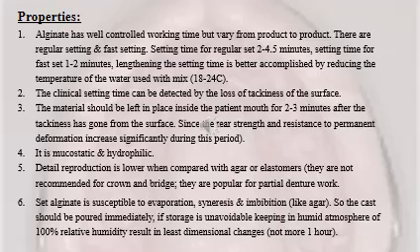2. Lengthening the setting time is better accomplished by reducing the temperature of the water used with the mix, from 18 to 24 degrees centigrade. The clinical setting time can be detected by the loss of tackiness of the surface. 3. The material should be left in place inside the patient's mouth for 2 to 3 minutes after the tackiness has gone from the surface, since the tear strength and resistance to permanent deformation increase significantly during this period. 4. It is mucostatic and hydrophilic.